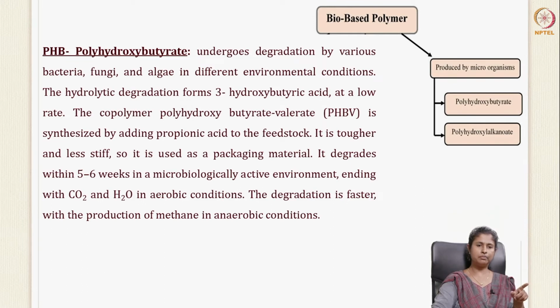The copolymer polyhydroxybutyrate valerate is synthesized by adding propionic acid to the feedstock. So this is tougher and less stiff, so it's used as a packaging material. It degrades within 5 to 6 weeks in a microbiologically active environment, ending up producing carbon dioxide and water in aerobic conditions. Under anaerobic conditions, with the production of methane, the degradation is even faster.